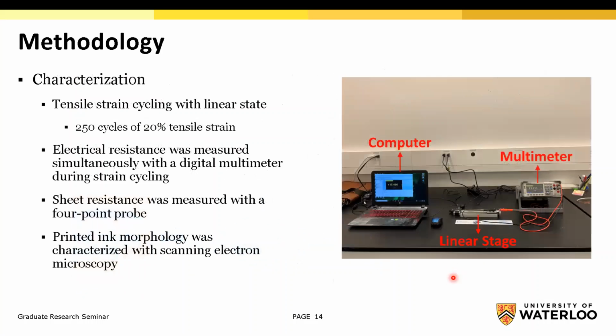For the characterization of stretchability, we used tensile strain cycling with a linear stage, 250 cycles of 20% tensile strain, with electrical resistance measured with a digital multimeter simultaneously during the tensile straining. Sheet resistance was measured by a 4-point probe, and printed ink morphology was characterized with scanning electron microscopy.